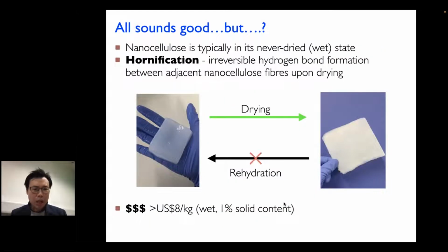So the greatest challenge with nanocellulose processing is the irreversible hydrogen bond formation. When you have wet state, when you dry it, it turns into a piece of paper, you put them in the water, it doesn't go back to the rehydrated state. Second problem is that it is very expensive. We don't know the exact price at the moment, but loosely speaking, $8 per kilogram wet is about the ballpark figure. So that's 1% solid content. If you basically take the number divided by 0.01, that gives you the dry state value. And that is too expensive for any useful materials, right?